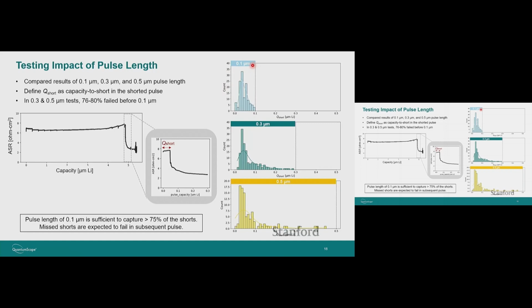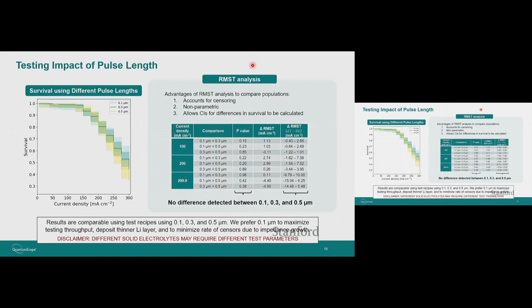We then look at that data statistically by overlaying the survival curves. And as you can see visually, they overlay quite well. When we do the quantitative analysis in the table on the right, what you would see quantitatively and statistically is that there are not significant differences between these populations. The way we quantify this is a technique called restricted mean survival time that I'd be happy to get into if there are questions, but it is a technique in survival analysis.